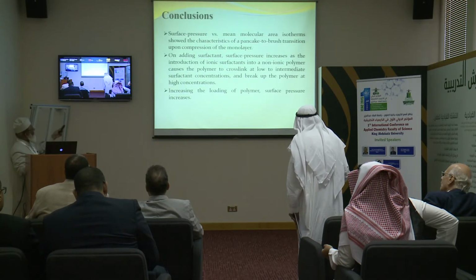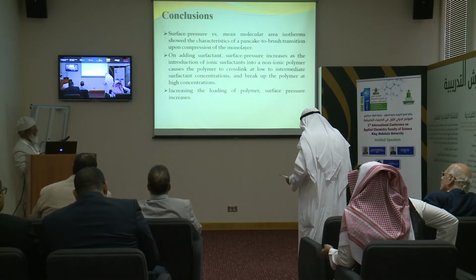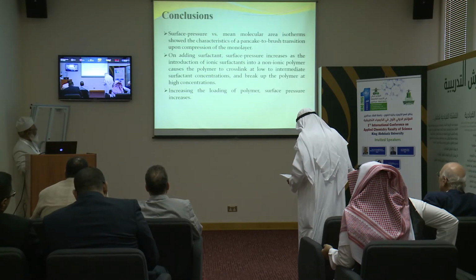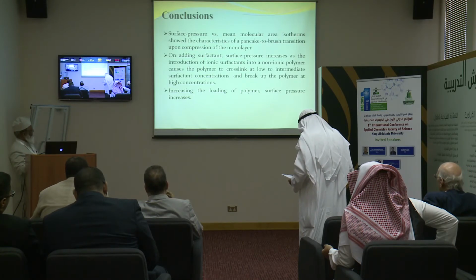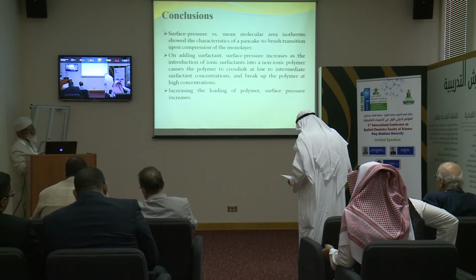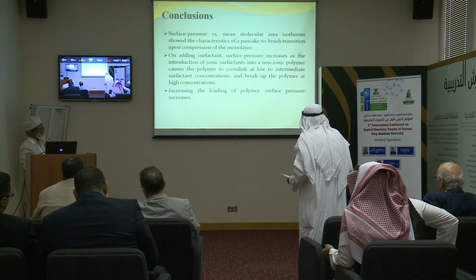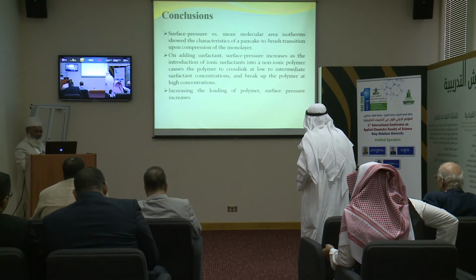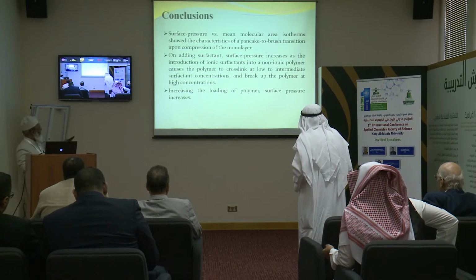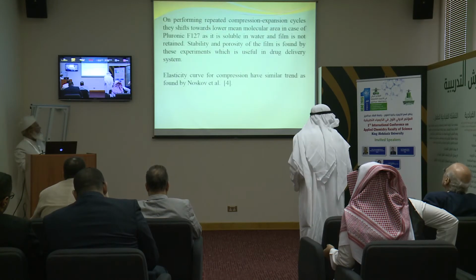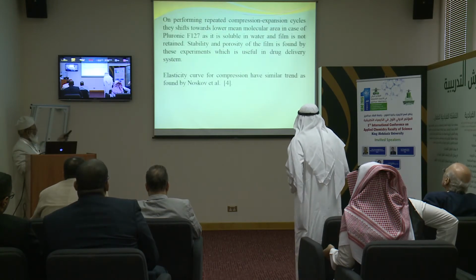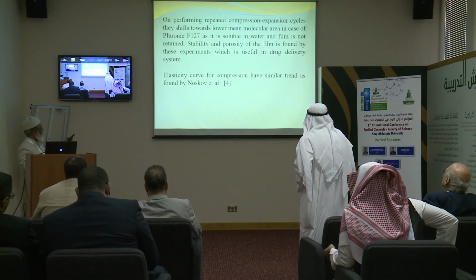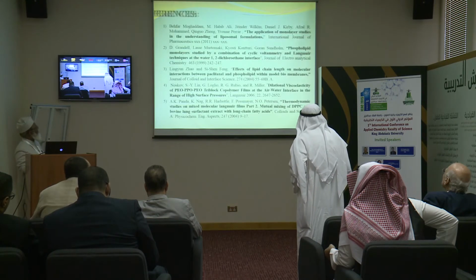The important conclusions are that on adding the surfactant, surface pressure increases, as the introduction of ionic surfactant into a non-ionic polymer causes the polymer to cross-link at low to intermediate surfactant concentration and break up the polymer molecule at high concentration, and also by increasing the loading of the polymer, surface pressure increases. The elasticity curve for compression has a similar trend as found by other workers.